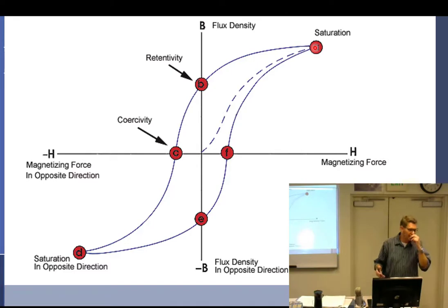So let's say it's a crankshaft inside of the head shot. I hit the head shot at 4,000 amps or whatever. That's a lot, but if it was 4 inches big, it'd be fine. So I have this huge magnetizing force, and I'm going to get saturation inside the part. Then the Magnaflux machine shuts off after half a second, and what's left is right there.